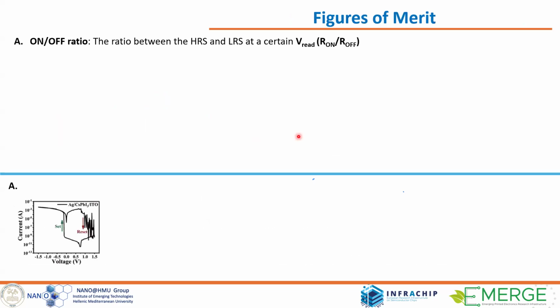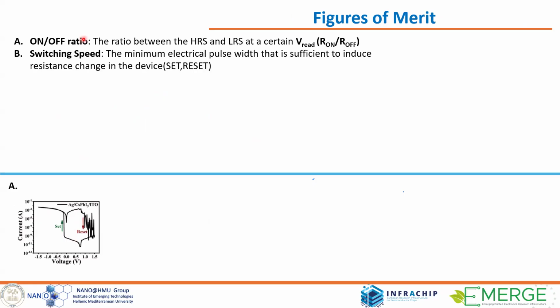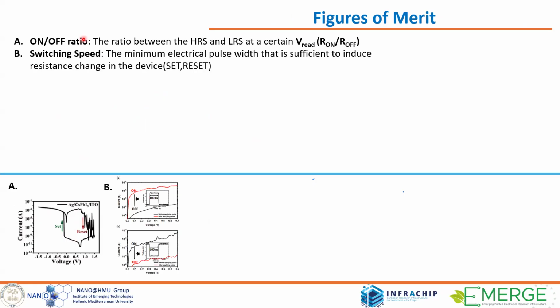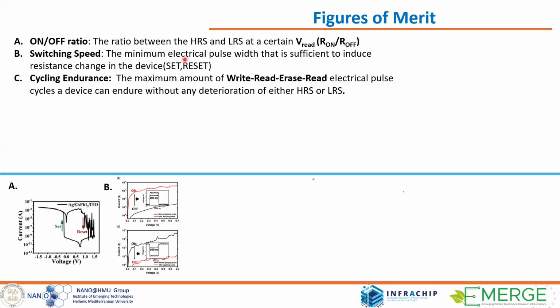Some details here. Now, what are the important key performance indicators, what we call KPIs? Of course, the ratio between the low resistance and the high resistance state. The higher the ratio, the better, of course. The second parameter is the switching speed, so how fast we can switch the device between high resistance and low resistance. Then the cycling endurance: how many times we can go between high and low resistance state. So it's an indication of the durability of the device.